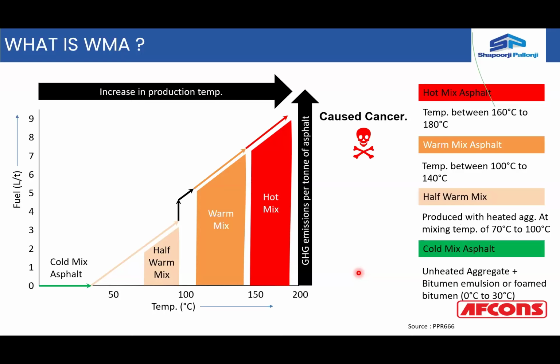Because by adding these additives, what happens is it increases the ability of the binder to coat the aggregate, and also controls the rate of loss of temperature in the mixes. So unfortunately, we had no option but to reduce the production temperature by 30 degrees. If you are not reducing the temperature and roll at a higher temperature, waves will come on the surface which are not visible to you. Once the mix cools, you can see the waves, which are generally noticed during the test called the profilometer test. So this was the difficulty if you're not able to control the temperature by adding the warm mix additives.